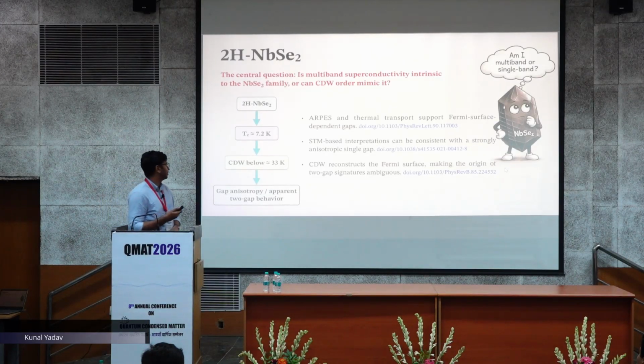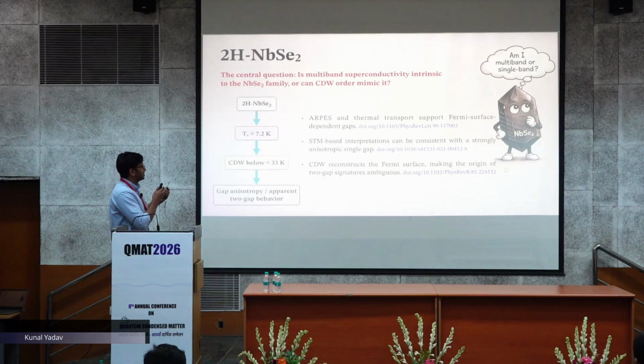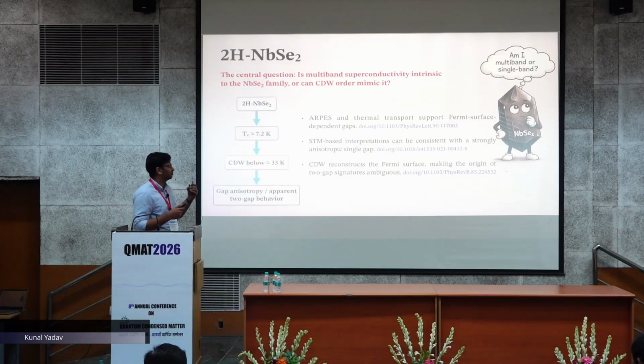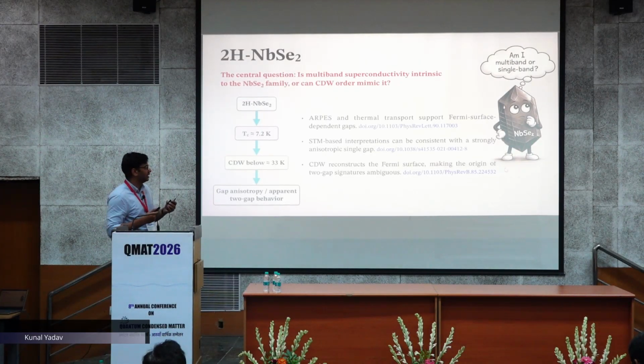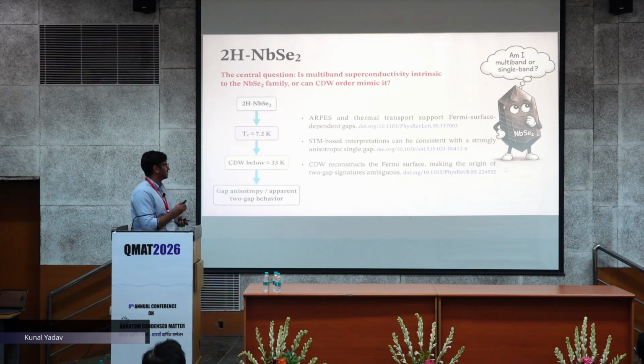well-known layered superconductor, whose superconducting transition temperature is 7.2 Kelvin, and it also exhibits CDW ordering at 33 Kelvin. But the debate is that some papers, ARPES and thermal transport, support multiple Fermi surface dependency, which shows that it is a multi-band superconductor. Other measurements like STM-based interpretation show that it is a strongly anisotropic single band superconductor.